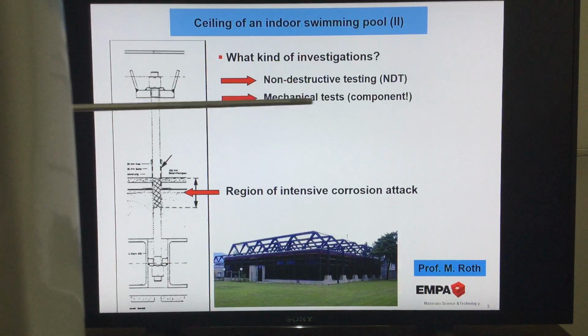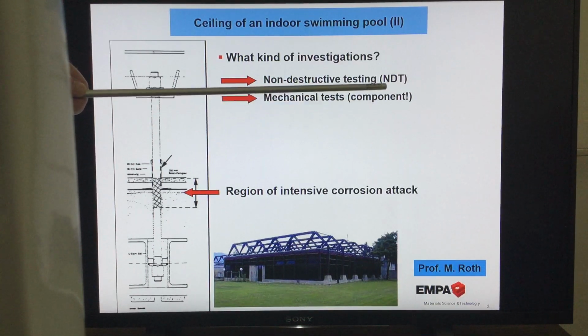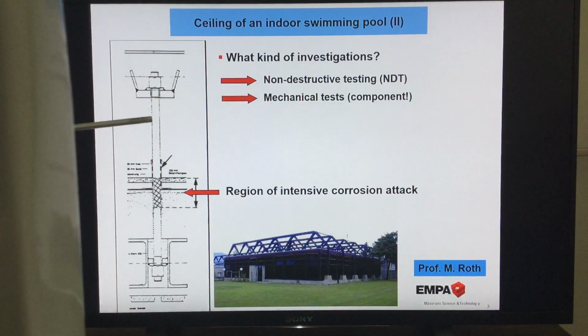Mechanical tests, a tensile test, but it's very important to use the component, not any specimen cut out from it, that tells you nothing. We have to make a mechanical tensile test with the whole component, and for this we have big enough machines available. Because it's clear, these mechanical tests on the component will tell us the result if the values for the ultimate tensile strength and the yield strength are fulfilled or not.